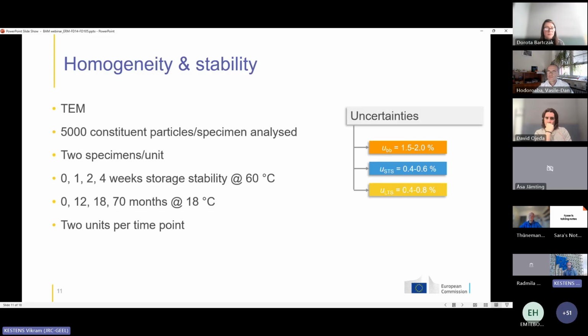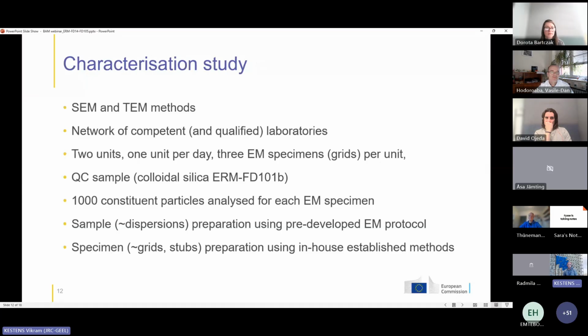And on the right-hand side, you can see some uncertainties. The uncertainty for homogeneity varied between 1.5 and 2%, depending on the material and depending on the measurand. And for the stability, you can see that the uncertainty ranged from 0.4 to about 0.6, 0.8%. So very small.